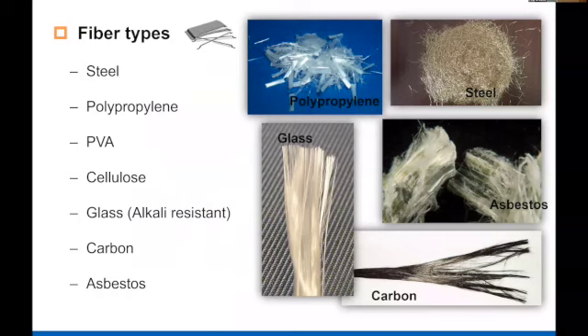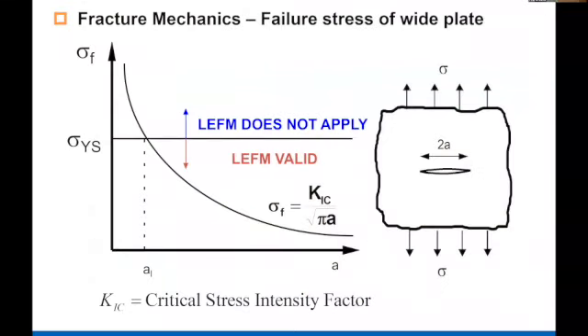The idea behind fiber reinforced concrete, at least initially, came from the classical concept of brittle material. When you look at the brittle material using the Griffith fracture criteria, if you look at the relation between fracture and the flaw size, the smaller the flaw size, the higher the tensile strength. So the thinking was that if you use fibers as opposed to prestressing bars or reinforcing, you can keep them closer. Initially the fibers we were using, and still using, in fiber reinforced concrete are about 30 to 40 millimeters long, with an aspect ratio of about 50 to 100.